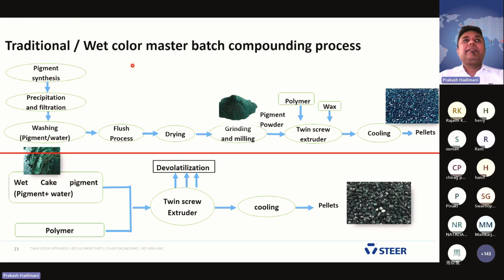See, the traditional dry pigment and the wet pigment color masterbatch compounding processes. At the top, we get the pigment by synthesis, precipitation and filtration. Then after this, we neutralize the pigment with water and adjust it. After washing the pigment, there is 60 to 70% water and the remaining 40%, or sometimes 30%, pigment in this wet mass. If you take it out from here, you can straight away put it into your twin screw using a side feeding mechanism, also dewatering, so that your job is done. You can save energy and your dispersion quality is fantastic.